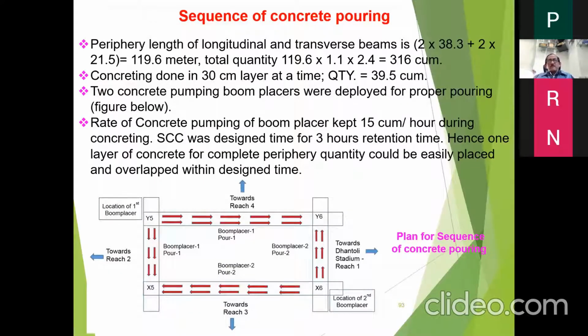The peripheral length of longitudinal and transverse beams, all was calculated, concreting done in 30 centimeter layers, quantity 39.5 cubic meter. 2 concrete pump boom placers were deployed, location of the first boom placer, location of the second boom placer, and the concrete flowed in this and this direction. And then there were some intermediate beams also. The rate of concrete pumping of the boom placer was kept at 15 cubic meter per hour during concreting. SCC was designed for a time of 3 hours retention, hence the layer of concrete for the complete periphery could be easily placed. So that time was calculated.